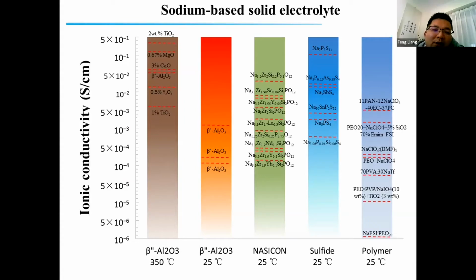So this figure shows the different solid electrolytes with different ionic conductivity. From this figure, we can see, of course, polymer, the ionic conductivity is low, but in the case of sulfide, it's unstable in the air, also in the moisture. So therefore, the NASICON structure, also the beta alumina, has a relatively high ionic conductivity. But in the case of the beta alumina, at high temperature it's okay, but at low temperature, the ionic conductivity is still very low.